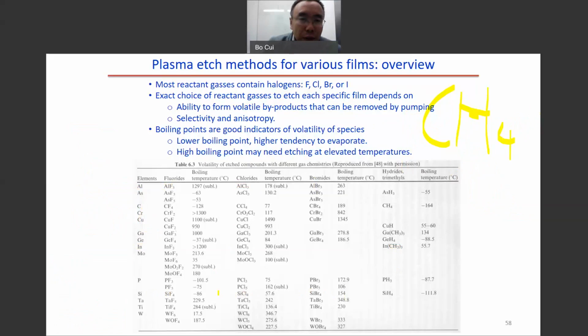Another example is chrome. We know that chrome is the material for the photomask. So how to etch away the chrome? Fluorine gas does not work, because it does not form any volatile product. But CrO2Cl2 is volatile, with a boiling temperature of 117 degrees.